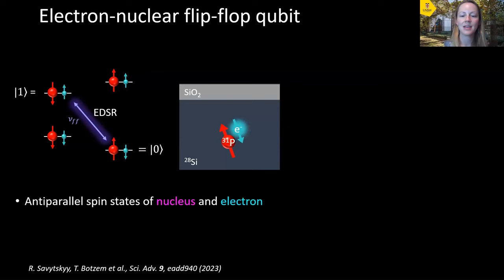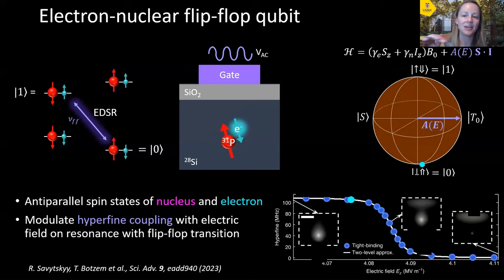And we can drive this transition by applying an alternating bias onto a gate above our donor that draws the electron wave function up and down. So it modulates the position of the electron with respect to this donor nucleus. And this changes the hyperfine coupling between the donor electron and the donor nucleus. And because this hyperfine coupling term is transverse in the spin Hamiltonian, if we can drive this electric dipole spin resonance on resonance with this energy splitting in the diagram, then we can flip and flop our nucleus and electron spins.